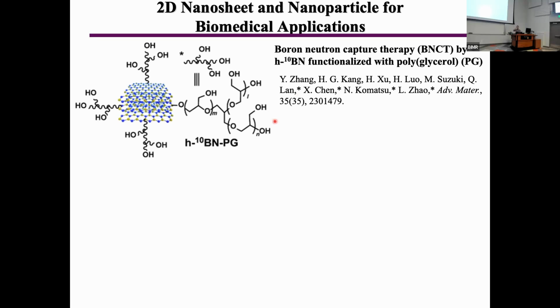So after I moved from Kyoto University to the Shiga University of Medical Science, we started to find more appropriate hydrophilic polymers for the surface of the nanoparticle. And then we found that polyglycerol is more appropriate than polyethylene glycol. That was published in 2011 in Angewandte Chemie, and afterwards we tried to apply this hydrophilic polymer to various kinds of nanoparticles. This is one example. Of course, after functionalization with PG, it has enough dispersibility for in vivo applications. And we use this for boron neutron capture therapy, BNCT.